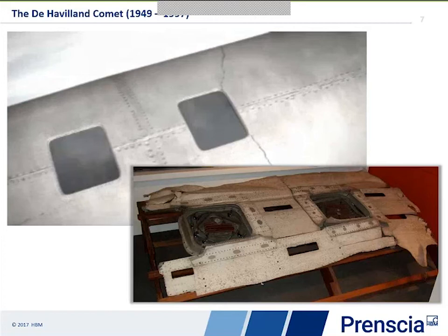And we can start to see where fatigue cracking developed. In that top picture, you can see an artist's illustration from Channel 4, where you can see the cracks starting at those re-entrant corners and growing to form the collapse.